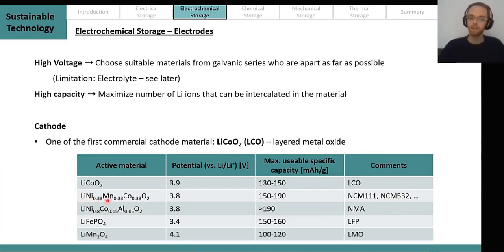Now, the two most modern materials in terms of high performance materials, I would say, is the so-called lithium nickel manganese cobalt oxide. Basically, it also forms these layers as we've seen before, but the cobalt can be partially replaced by manganese and partially by nickel. With this kind of strategy, we get a similarly high potential, but we can reach capacities of up to 190 milliamp hours per gram. And there is actually a variety of ratios from nickel to manganese to cobalt, all having slightly different properties. So these are typically abbreviated as NCM 111 or NCM 532, depending on the ratio of nickel to cobalt to manganese and so on.